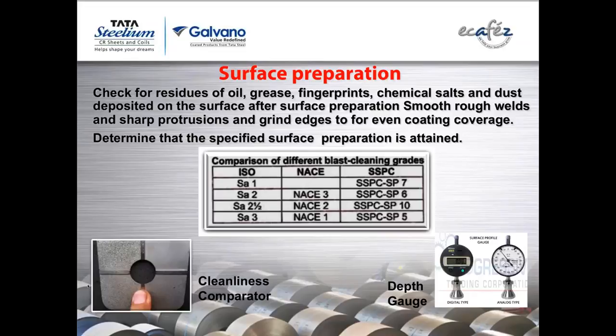SA2 and a half, we call near white metal. So you can see some gray patches and some white patches on it. But these gray patches are mill scales that are adhering to the base metal very nicely, so it's not very easy to remove those. Normally, in many specifications you'll find the blasting specification given as SA2 and a half. SA2 is commercial blast, and SA1 is what we call sweep blast or brush blast. Usually we do it on hot dip galvanized materials, where I cannot have more mechanical action, otherwise we will end up removing the zinc layers which are there for protection.